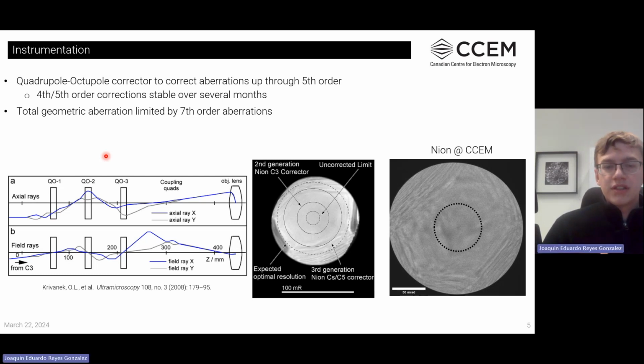This C3, C5 corrector allows us to actually adjust these fifth order aberrations. We typically don't have to very often. They're very, very stable for months on end, but we will have to touch them up perhaps once, maybe twice a year, just in case of little bits of drifting over time, or in case there's some kind of large instrumental error. It's something we don't need to do often, but it's just to maintain that very high performance. By adjusting these, we make sure that our total geometric aberrations are only limited by seventh order, so we can get these very nice probes out of our scope.